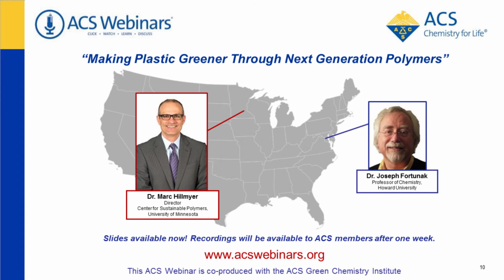So facilitating that initial breakdown by putting in hydrolytically more sensitive linkages through a copolymerization strategy, that is, polymerizing lactide with some other monomer that has weak linkages. We focused on the acetal linkage recently to do that, but others focus on different kinds of strategies to speed it up. To slow it down, you can also think about copolymerizations, and we've worked a little bit on this in the story I told you about polymenthide. That's an aliphatic polyester, but it has a much more hydrocarbon content, so it's a much more hydrophobic material.